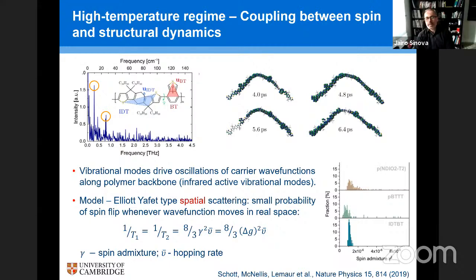Yeah, I think the big part of this is trying to calculate, which has not been done before, this spin mixture parameter, which depends a lot, by the way, on many factors, particularly on the angles between the molecules and the vibrations of the molecules themselves. Not so much. We haven't studied that because essentially you effectively do it perturbatively, where the spin-orbit coupling together with the phonons coupled together with this admixture gives you that.